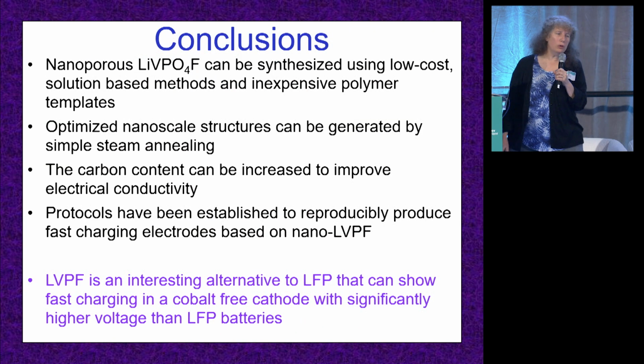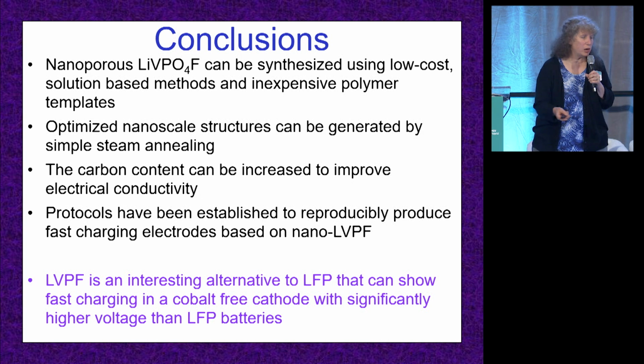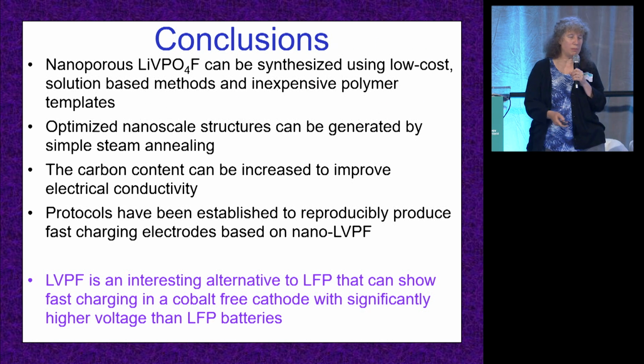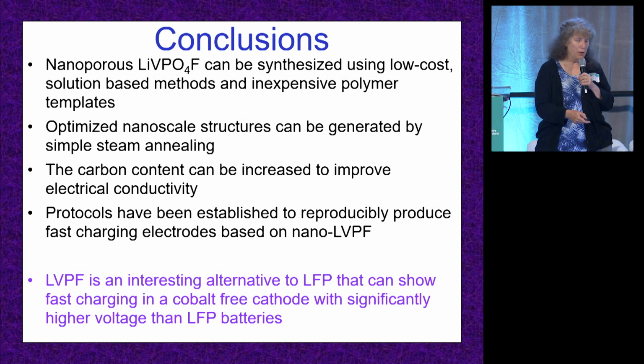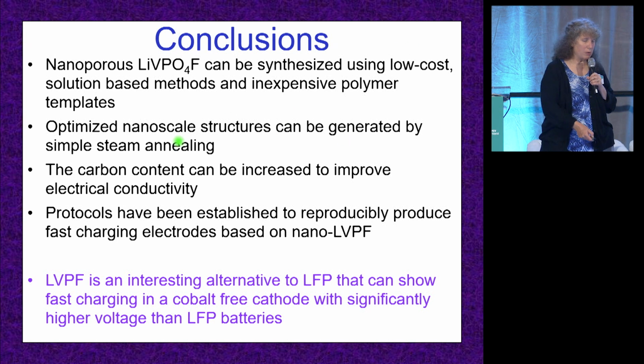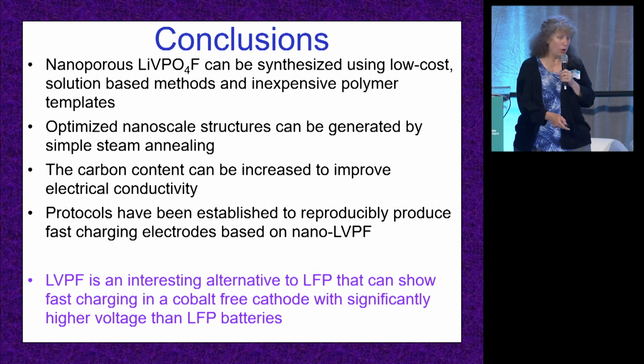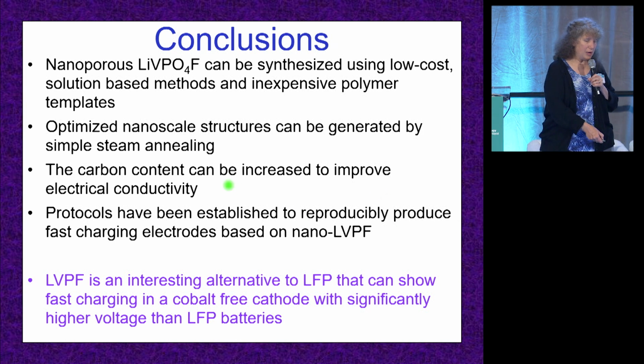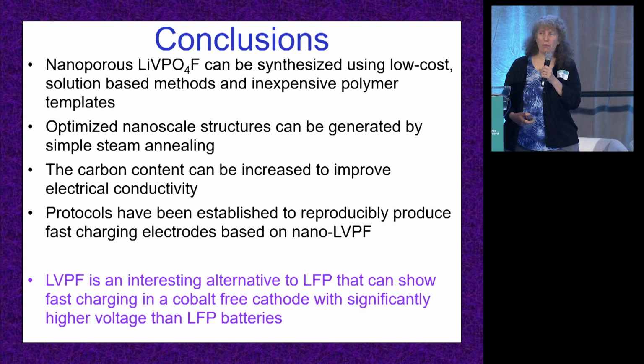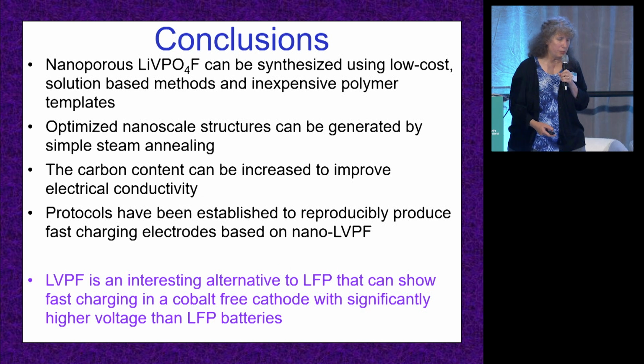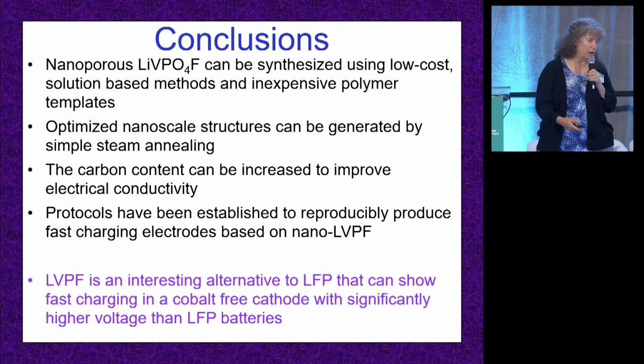Okay, so let me conclude. I hope that I've showed you that over the course of this project, we have been able to develop methods to produce nanoporous lithium vanadium fluorophosphate in a low-cost solution-based method with really low-cost polymer templates. We've optimized the nanoscale structure. We've optimized the carbon content. We've optimized the way to build these into batteries. And I think the net take-home message is that LVPF is a really interesting alternative to lithium iron phosphate that can show fast charging, is a cobalt-free system, and has significantly higher voltage capabilities than lithium iron phosphate.